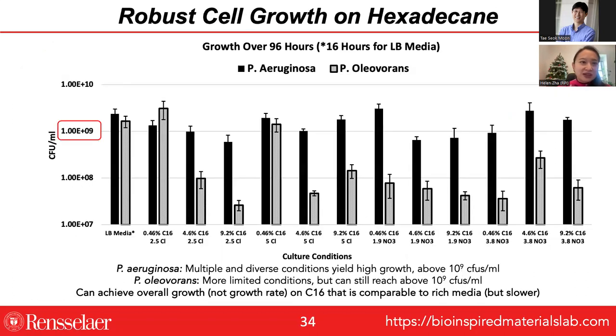And what we did find is these are CFUs in various culture conditions. We did find that Pseudomonas aeruginosa in particular was able to grow quite well using just hexadecane as a carbon source in the media. There are certain media formulations that do better and certain that don't do as well, but in general, we get pretty good cell growth at something close to 0.5% C16 in the media.